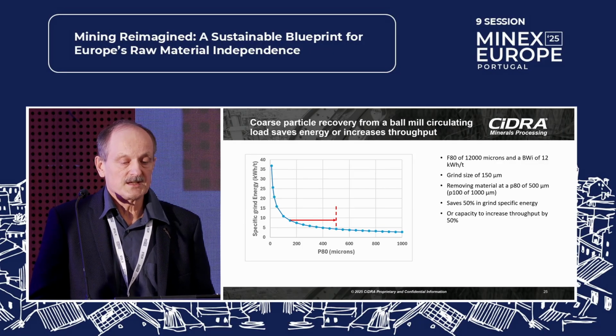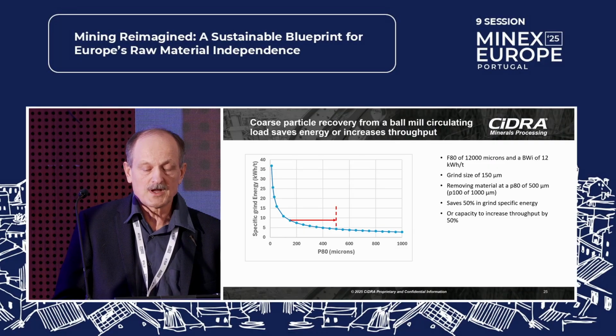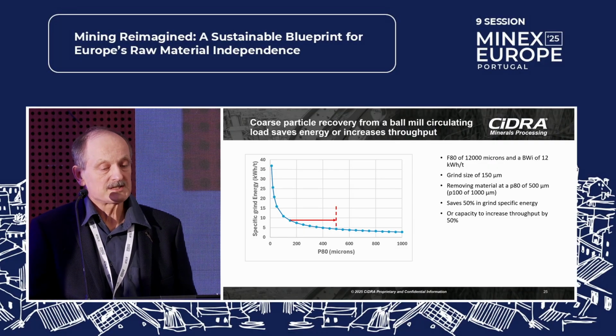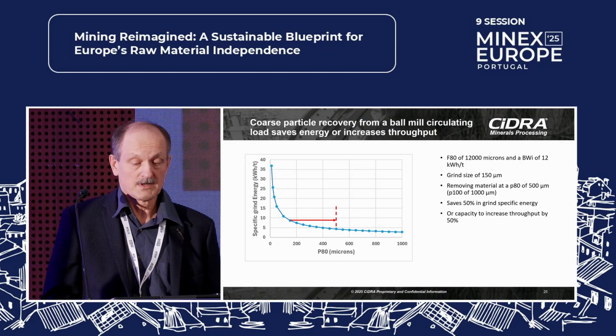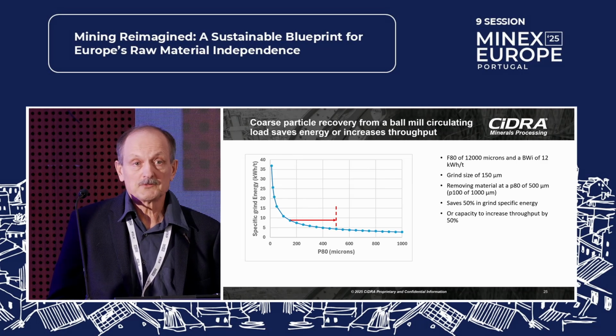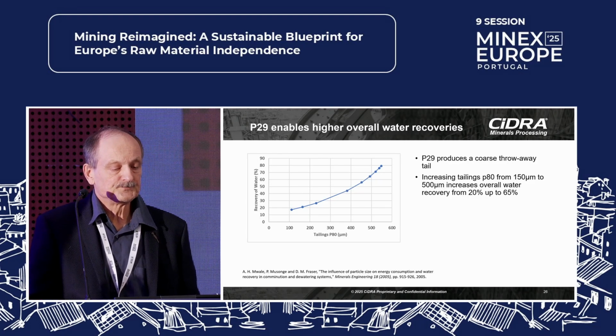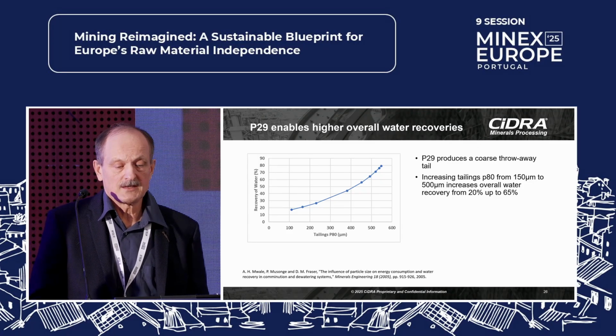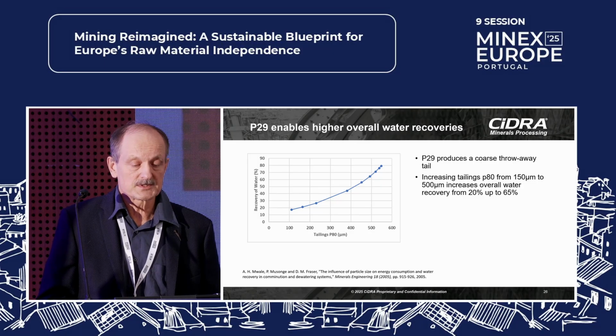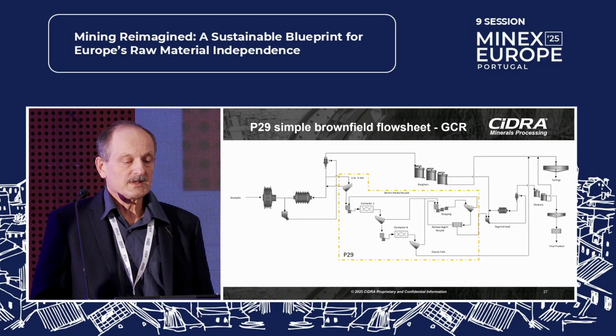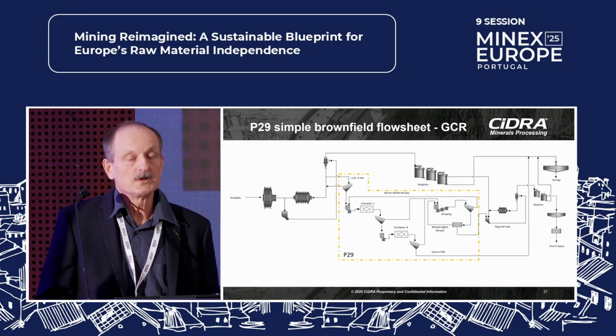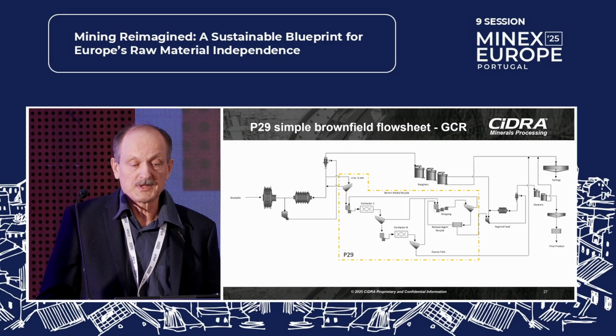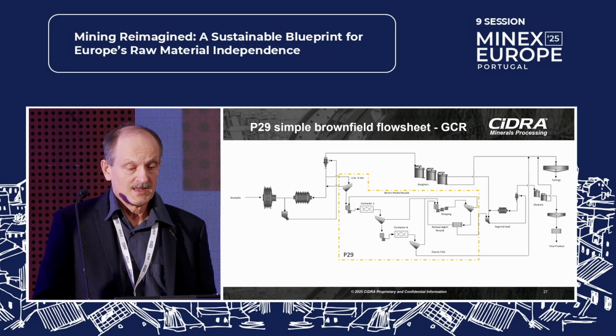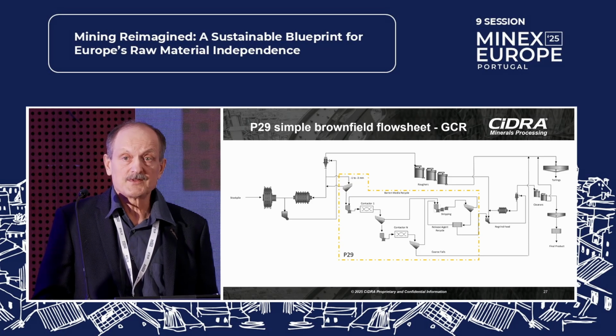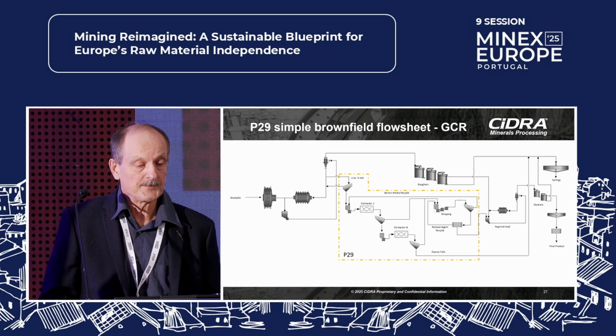So if we can increase the grind size, the P80 value from 150 to 500 microns, you are saving 50% in grind energy. Or you can increase throughput by that same amount. Also, we are providing coarser tails, and that enhances the water recovery, even triples it. So we typically take in a brownfield case the underflow, so we take part of the circulating load and handle it with the P29 process and capture that there. And the remaining flotation can be optimized for the fines better than earlier.